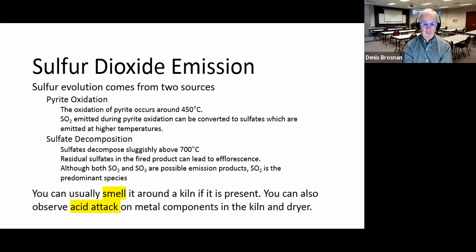So if you get corrosion on kiln cars or components in the dryer, things happening in the kiln, you'll know that you probably have acid gases. With sulfur dioxide, you'll also know by the nose, because your nose is very sensitive to sulfur dioxide. It has a bitter smell to it. So if you're walking around on the top of the kiln while it's in operation, you can just smell the sulfur dioxide up on top of the kiln.